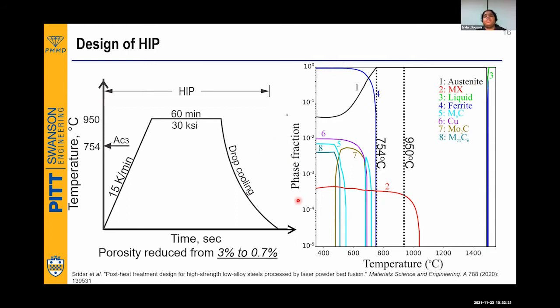These are all the different phases that are forming in this particular steel I'm talking about, as a function of temperature. I hope everyone is familiar with the AC3 temperature. The AC3 temperature for a steel is the temperature at which the material becomes completely austenite. The AC3 temperature for this steel is 754 degrees C as calculated using this CALPHAD method. However, due to errors, and because this is an equilibrium calculation while what we are doing, additive manufacturing, is a completely non-equilibrium process, to take all that into account we are increasing the austenitization temperature by more than 200 degrees C and setting a temperature of 950 degrees C.